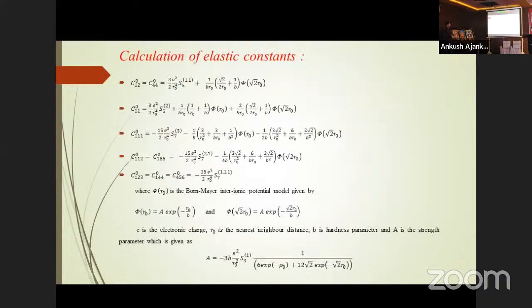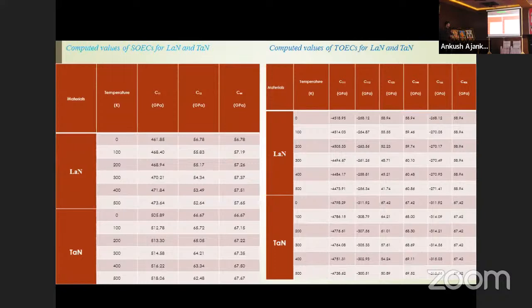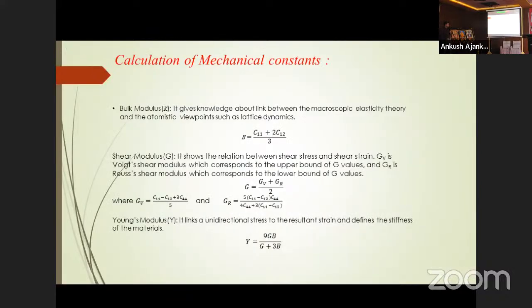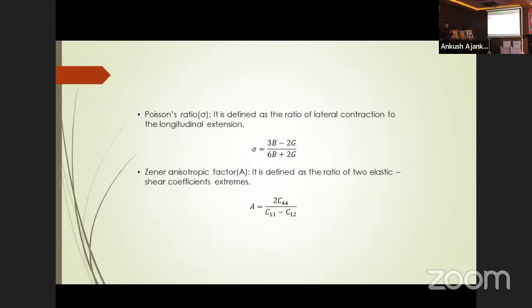In this slide, the formula used for the evaluation of higher order elastic constants has been presented, and the Born-Mayer interatomic ionic potential model is used for the evaluation. The computed values of second order elastic constants for lanthanum nitride and tantalum nitride have been tabulated in this slide. Further, with the help of the computed elastic constants, bulk modulus, shear modulus, and Young's modulus have been evaluated using these expressions. Poisson's ratio and the Zener anisotropic factor have also been evaluated using these relations.